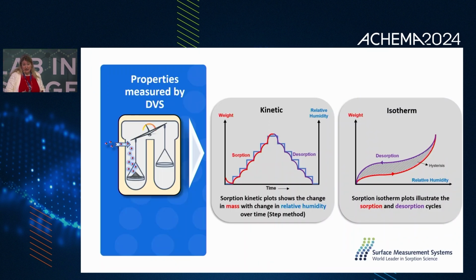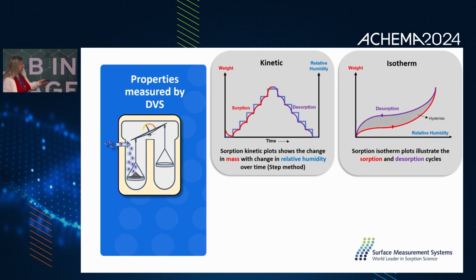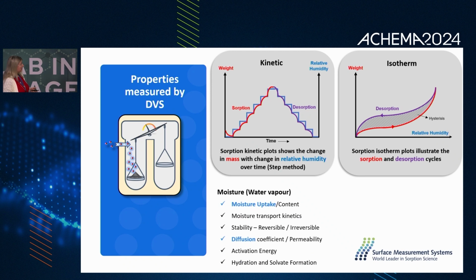For those who don't know about the gravimetric technique, the DVS has an ultra balance, which is quite sensitive, 0.1 microgram. You place the sample of interest on one side, as I mentioned, solid state, and the other side stays empty, which is the reference side. And as you can see, you can look at the sorption kinetics of different materials, and also the isotherm plots. You can use water vapors or organic solvents.